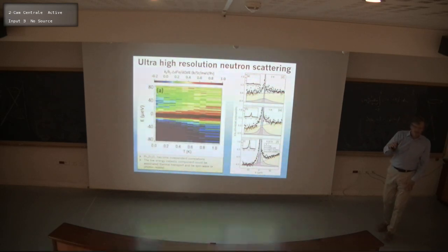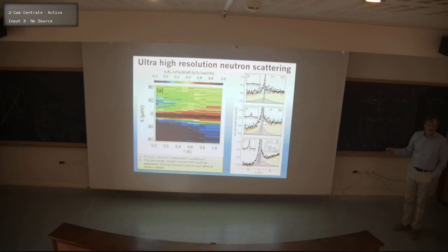What I think we can say is that whatever that thermal transport is, it's somehow related to 4f electron excitations, as opposed to nuclear spin processes, which could also have had a role. Because we see this, we can actually say that it's not a nuclear low energy excitation. It really is a 4f electron excitation. So there is actually quantum dynamics in that temperature range, but exactly what that is, we're not able to commit to, let's say, phonons as opposed to some form of a glassy spin wave type excitation.